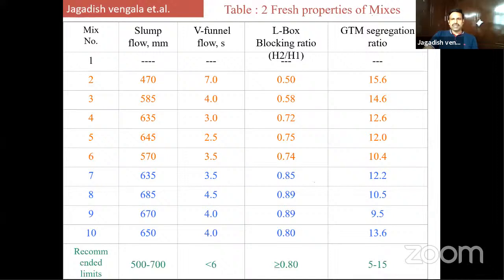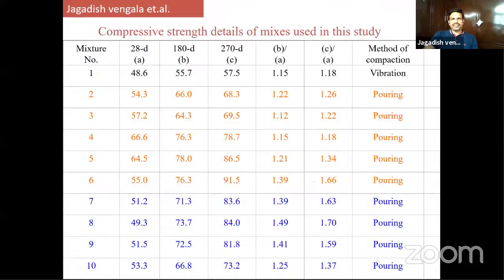These are the slump flow values. You can see the bottom mixes. V-funnel we got around 3 to 4 seconds. And the L-box blocking ratio is more than 0.8, and then GTM segregation ratio is between 5 to 15. Very interesting results, which I presented in 2003 in one of the international conferences conducted by Kumar Mehta in association with Ravindra Gettu.